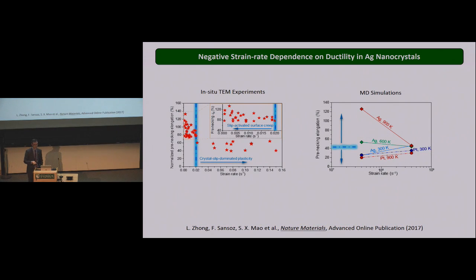Another thing, again, it's very hard to compare experiment and simulation because the strain rate between the two differs by about ten orders of magnitude. And so you cannot just say that what happened at high strain rate is the same at low strain rate. But still, we can compare the behaviors.